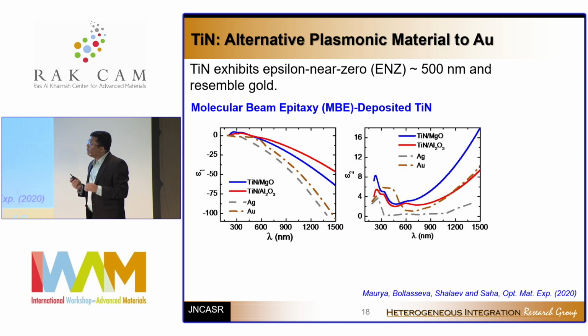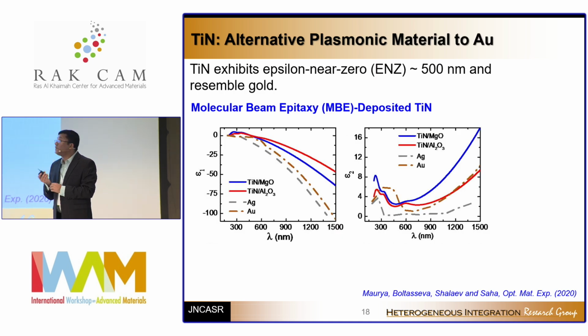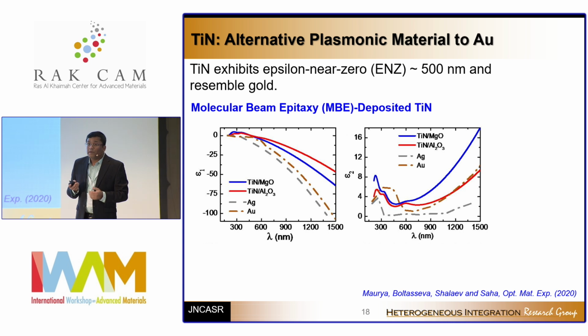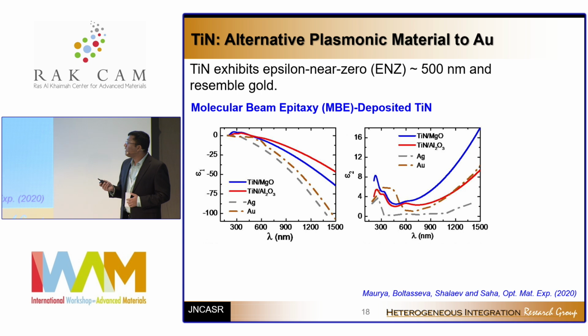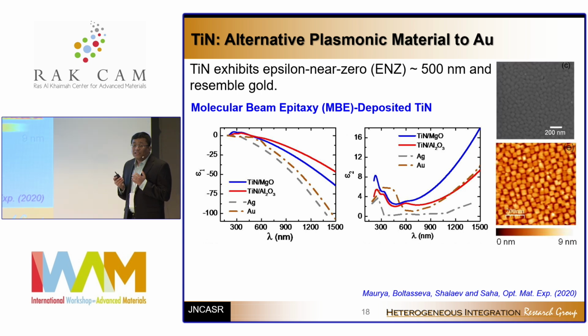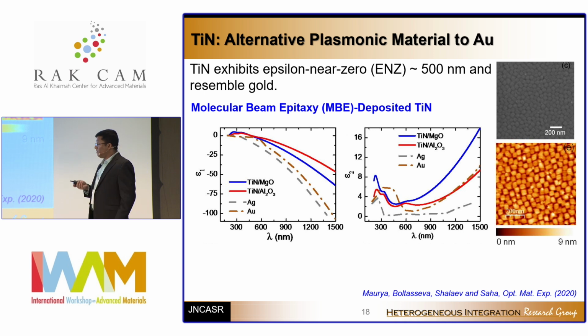Now, this work started when I was a student. Titanium nitride looks like gold, but its optical properties still needed to be established. So we have shown previously that titanium nitride has an ENZ frequency, or the crossover frequency, at around 500 nanometers, and that resembles gold. And we have shown many other applications at that time also. But one of the questions was always that titanium nitride had a high optical loss. So how to get around this?